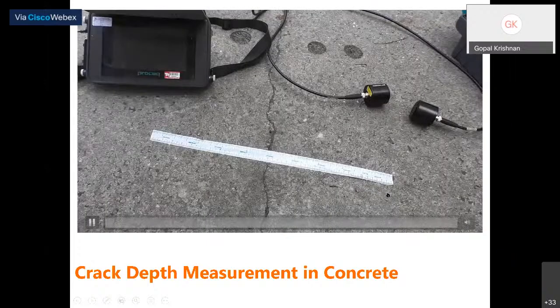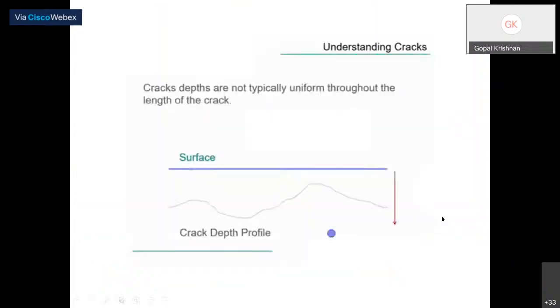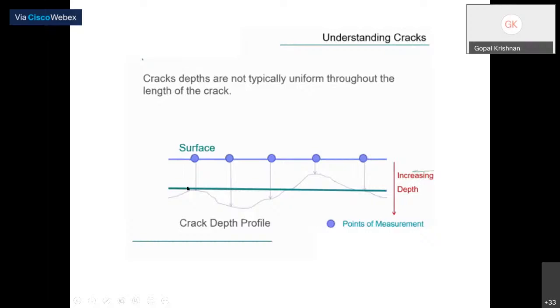For determining the crack depth, the crack may not be a straight line. The crack profile may zigzag, so we have to measure at several places and take the average to get the exact depth of the particular crack. We have taken several readings and then taken an average, because some of the cracks are shallow and some of them are deep.